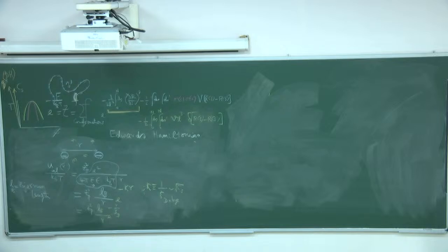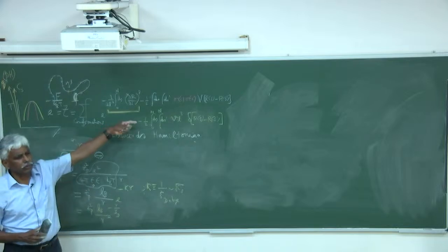Okay, so I have to bring this into our Hamiltonian. How do you do this? In addition to this, I have negative half, integral ds from 0 to N, ds prime from 0 to N, and then this term: Zp squared lB over the magnitude of r(s) minus r(s prime), times e to the minus kappa times the magnitude of r(s) minus r(s prime). Yeah, that's good enough. That's our Hamiltonian.